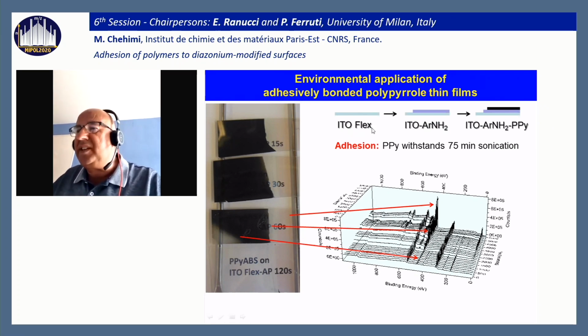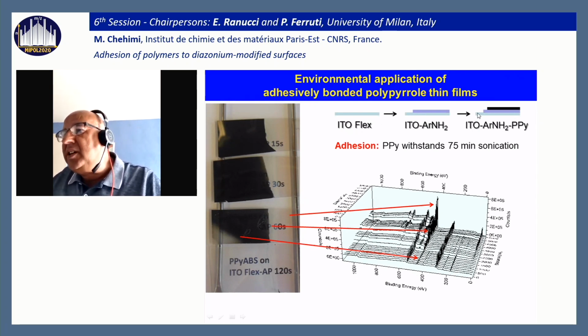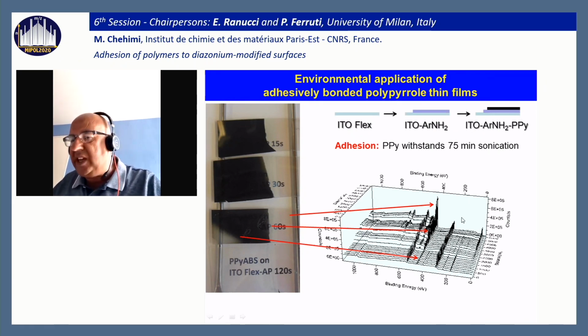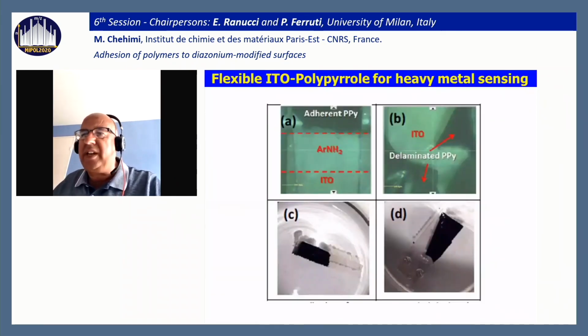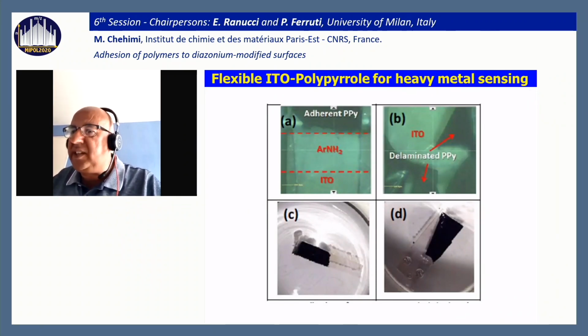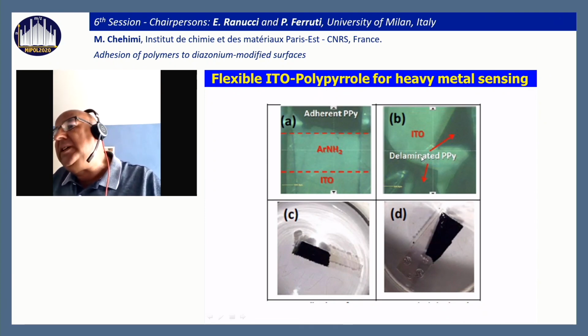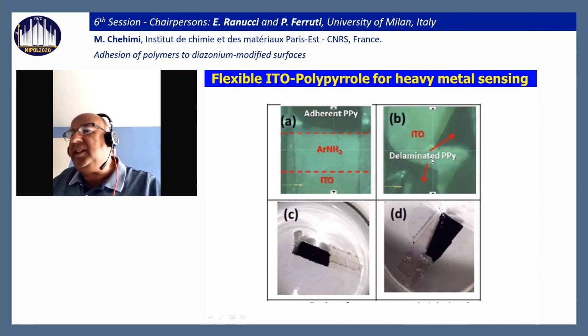We have scanned the surface, from the bare naked ITO to the aryl layer and then the polypyrrole, by XPS to check the uniformity of the deposited polypyrrole layer. For example, in XPS, when we start the vacuum, if there is no adhesive layer from diazonium salts, the polypyrrole film is simply delaminated. It is sucked by the vacuum, but here it is very stable, and we can see the interface under the CCD camera of the apparatus.